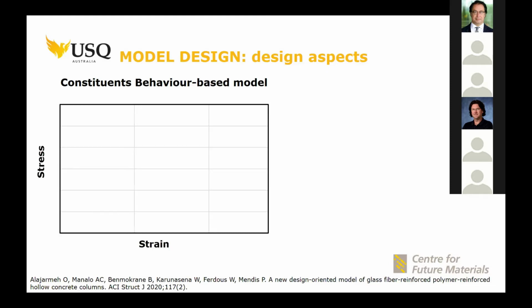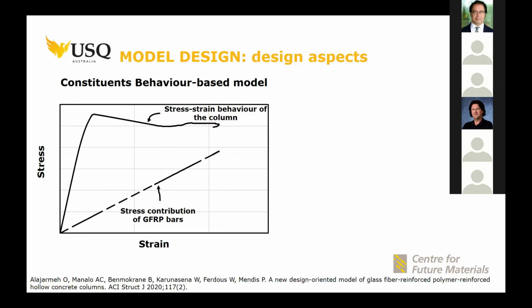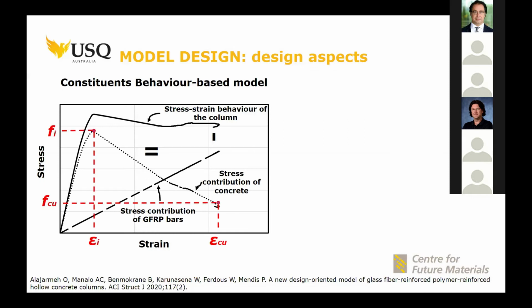We based that model on the constituent behavior of the material, starting from the behavior of the whole column. If that is the stress-strain behavior of the column, and we know the stress contribution of the GFRP bars relying on the elastic behavior of the bars, after subtracting the two contributions, we can find the stress contribution of the concrete. That concrete behavior is based on two critical points, and you can see here the peak point and the fracture point.